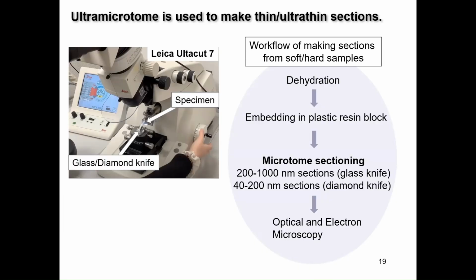And for the microtome sectioning, if we are making sections for optical microscopes, we use a glass knife. We can get 200 to 1000 nanometer thickness sections. And if we are doing sectioning for TEM, we use a diamond knife, and we can make 40 to 200 nanometer thickness sections. So it depends on the section thickness. They can go to optical microscope or transmission electron microscope.